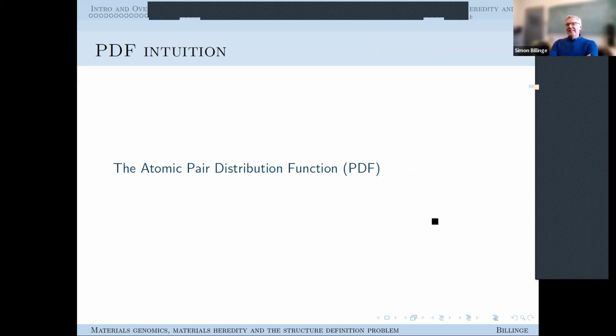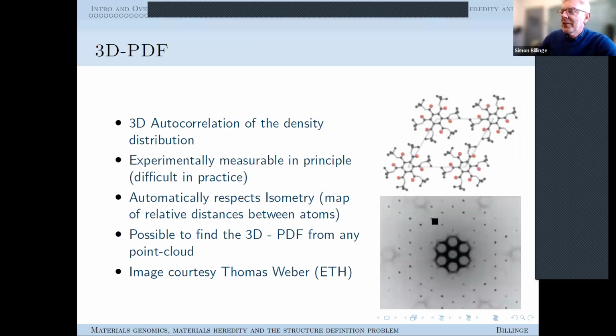The one that's my favorite is this atomic pair distribution function. And the reason is that I spent my entire career basically developing this as an experimental method. So very briefly, what is the PDF? Basically, it's the three-dimensional autocorrelation of the density distribution. What I do is I define my material as a point cloud, where the atoms are the points and they exist in some Euclidean space. So I've got my 3D point cloud, and then I take the autocorrelation of that point cloud. So I convolve it onto itself, and that is the PDF, the 3D PDF.